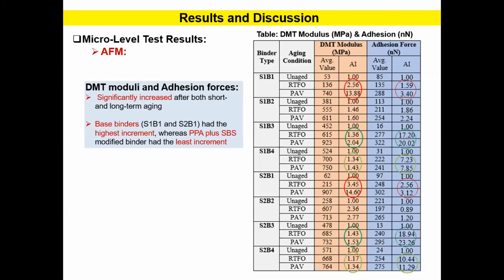However, there is a trend among all of the asphalt binders that regardless of their aging conditions and binder type, the DMT modulus and adhesion force values are increased due to both short-term and long-term aging.